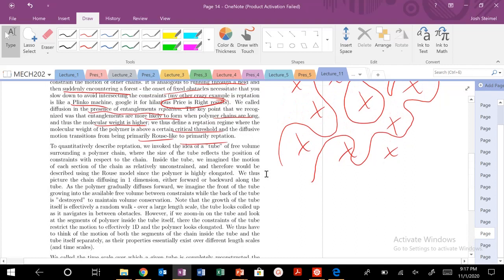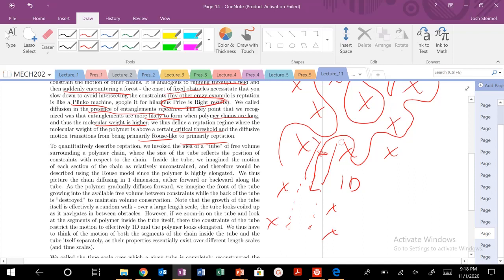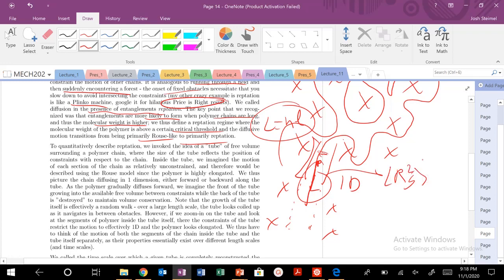We looked at this idea of motion of a tube — there's a tube of free volume surrounding the polymer. Your polymer can move inside a tube, but it's going to move in essentially one dimension. Inside the tube we have 1D motion, and we move until we create a whole new tube navigating topological obstacles. We're going to move a tube length, which is our contour length L. So we move in 1D this entire distance L equal to our contour length. But our center of mass of our polymer is going to move a distance equal to our radius of gyration — that's the 3D motion when we zoom out.